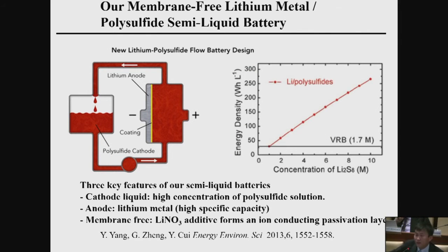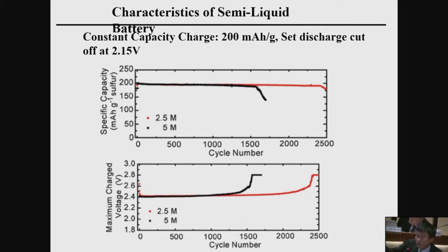So I want to show you one example. It's actually using a polysulfide redox molecule. Its solubility is 5 times that of the vanadium redox. And then this polysulfide, the red color liquid, in contact with lithium metal, forms a self-decomposition compound. It's a lithium ion selective membrane by itself. So you don't have to use an expensive membrane anymore. And this one has about 5 times higher energy density compared to the vanadium redox flow. The sulfur is cheap. This has the possibility to give you a grid scale storage solution.